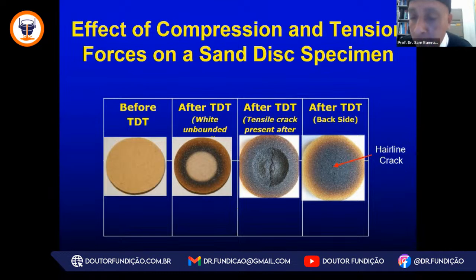During the thermal distortion test, we know exactly what time and at what temperature the crack occurs and when these changes occur. This is the analytics that drives when that casting needs to freeze, because if that casting is still liquidous when there is cracks, when that hot sand has opened, literally that crack will close when that mold is left to cool. But in the liquidous state, that molten metal is picking up that crack to cause us defects.